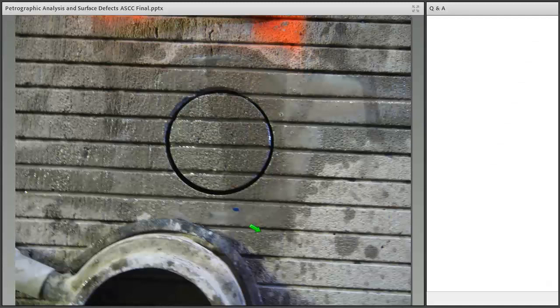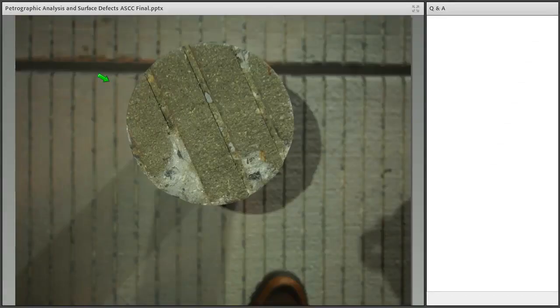This is a core taken from a different airport and laid out with great care, and you can see here the core has been taken nicely. There's some nicely cut-in texture, and if you look at the core after it's been removed, the removal process has done some chipping. Without this initial photograph, you would think that there may be some spalls occurring in that pavement, all as a consequence of the sampling technique.